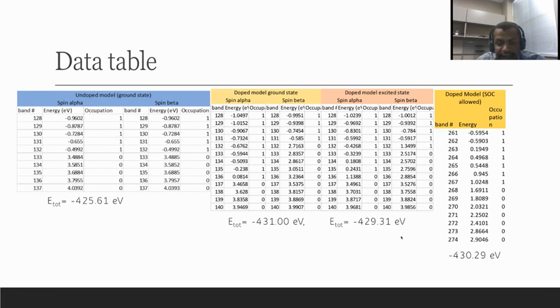That's because the spin acquires two parameters. In the case of spin alpha, the parameter for spin alpha would be 1 and the parameter for spin beta would be 0, and in the case of beta, it would be the opposite. But in this case, they are also allowed to contribute maybe at 25%, 75%, since it's a vector. So the square root of the sum of the squares of these two parameters would give 1 if there is an electron and 0 if there is no electron. So in this case, we just have HOMO and LUMO orbitals. Next slide, please.